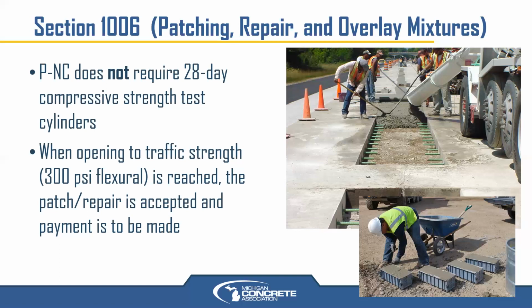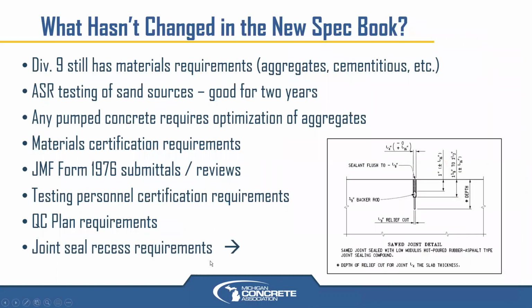And for P-NC, you only need 300 PSI, again, done in the field with a similar curing condition as to the patches themselves. If they're covered with blankets, cover the beams with blankets. If they're just sprayed with curing compound, spray the curing compound on the beams. But as soon as you get 300 PSI, the repairs are open to traffic, and full payment for that item is payable to the contractor. No 28-day cylinders.